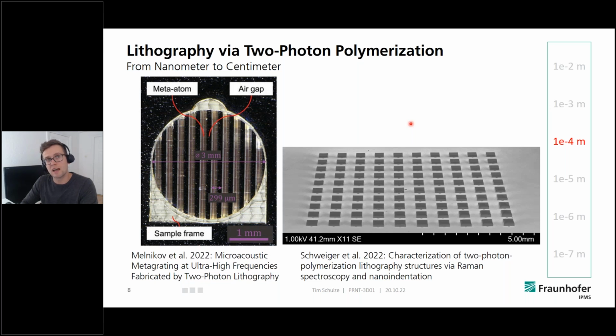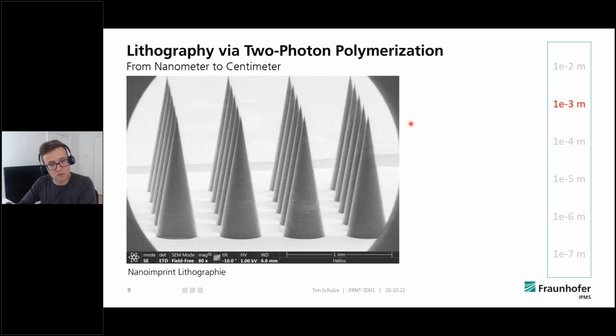The idea is to use, so let me start differently. We are able to change the E modulus, so the elasticity of our printed structures by addressing different printing parameters. For instance, if we use low laser intensities, we're able to print structures that are a little bit softer, have a low Young's modulus, or if we increase the laser power, then the structures are a little bit stiffer. And with Raman spectroscopy, we were able to measure this stiffness. And like I said, we are currently trying to establish a process to determine the elasticity of our objects without even touching them. And a next step up, this is also a project we have done.